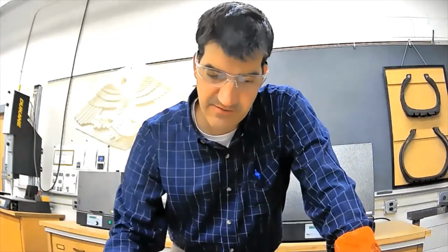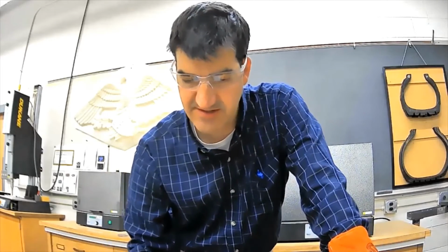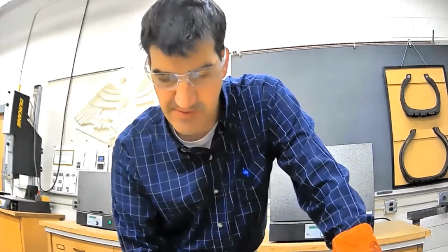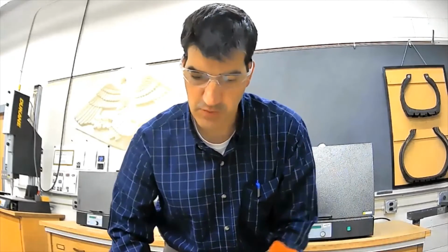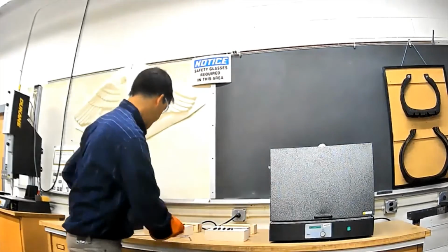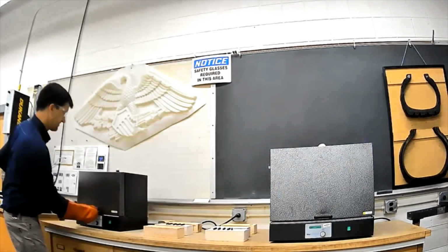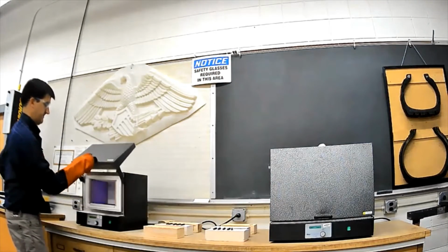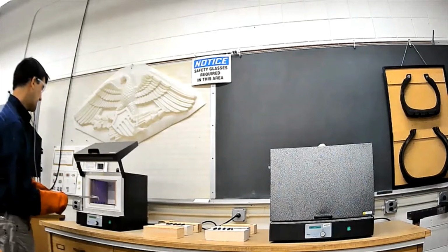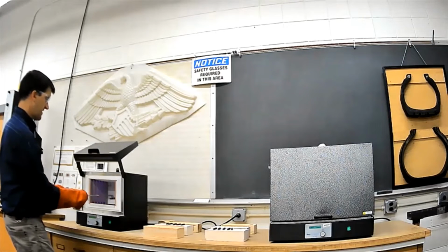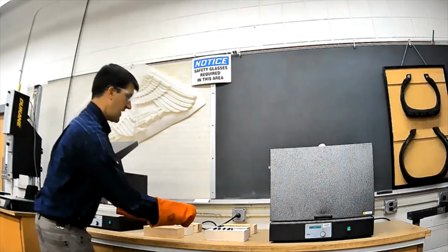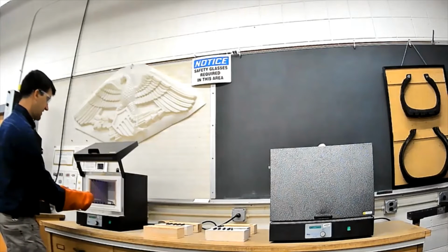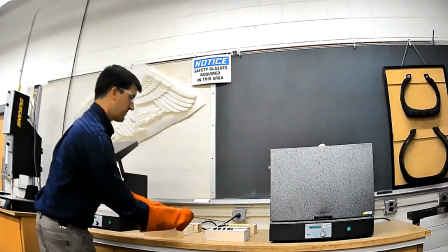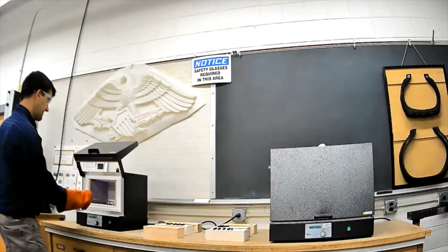All right, it's been 30 minutes and we're back and ready to do step 10. Step 10 says to remove the specimen 2s from the low temperature furnace and place them on the cooling bricks. So let's go ahead and do that. All right, so there's definitely a difference in the color. They're very hot, but they are not glowing cherry red like the ones were before from the high temperature furnace.